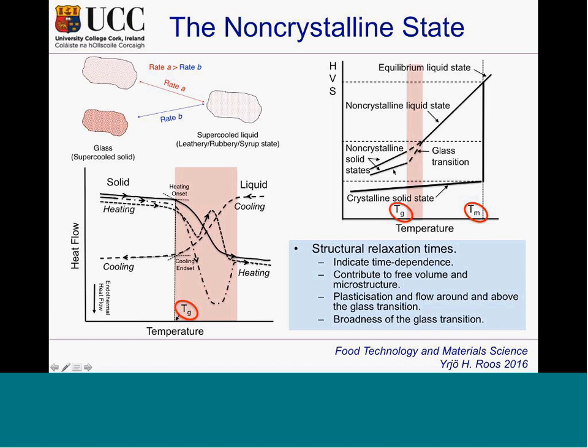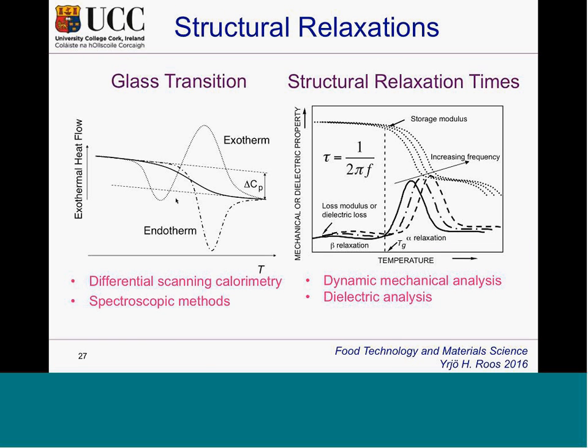What I'm interested in is how fast these relaxations happen about the glass transition onset. The onset is a measure of a temperature value where we start to see real-time changes. And we can explain the difference between differential scanning calorimetry and, more importantly, what happens about the transition in dynamic mechanical analysis or dielectric measurements.